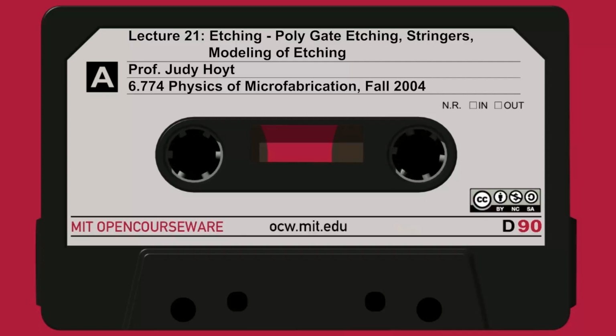Now, why would anyone want to do this? You put down poly, you pattern it, and then later on you're going to remove it. Sounds kind of crazy. Why didn't you just put the metal down to begin with? Does anybody have any ideas on why you might want to use poly and then stick the metal in at the very end? Well, there's a couple reasons. One reason is we know how to etch poly perfectly, right? We've spent the last 20 years getting perfectly vertical sidewalls. So people know how to etch it. The second reason is poly can go up to very high temperatures.